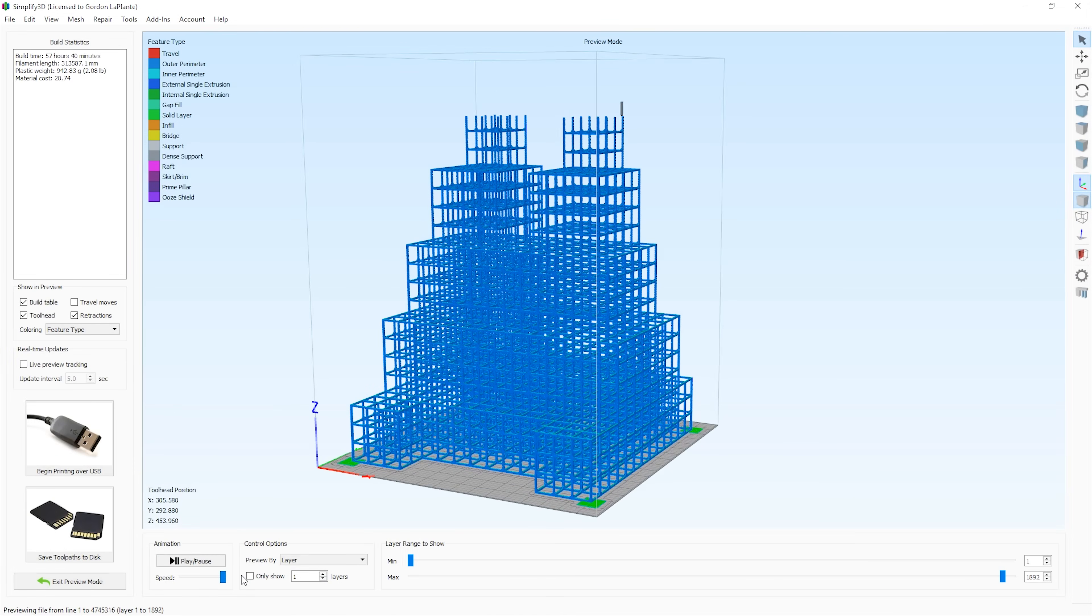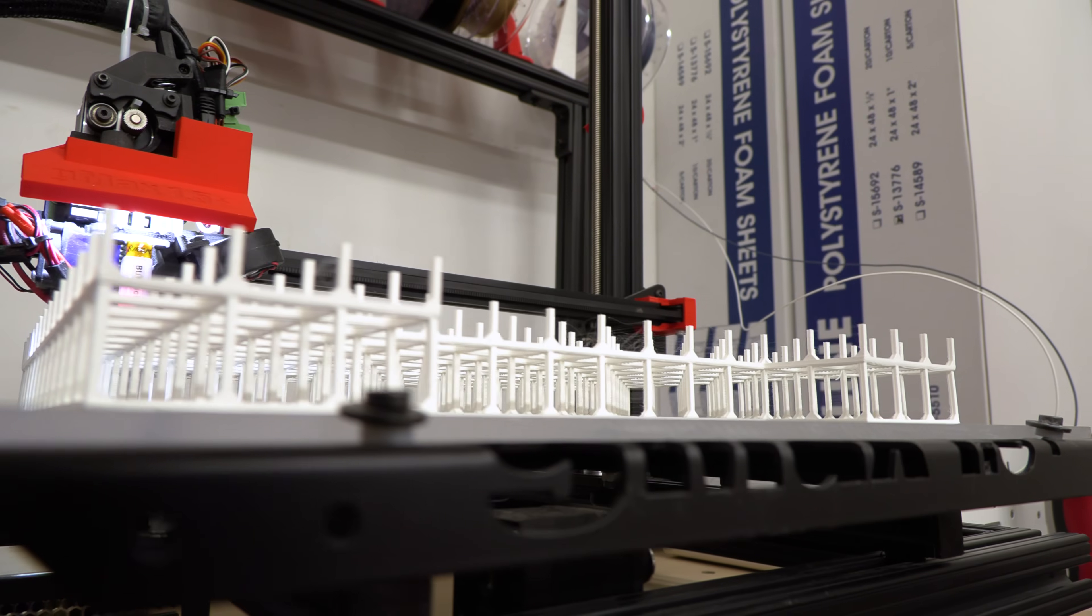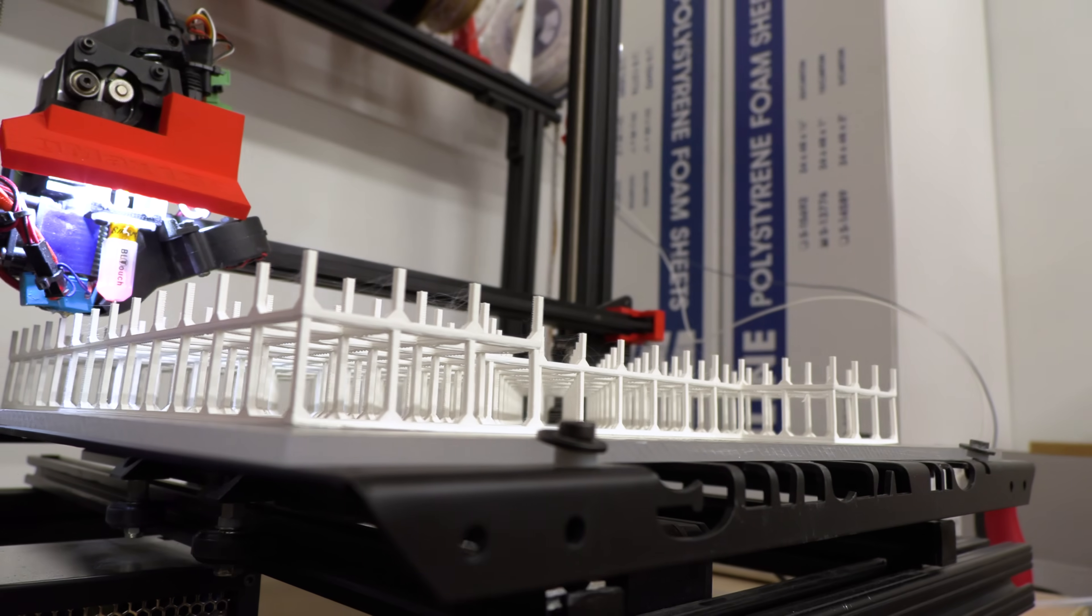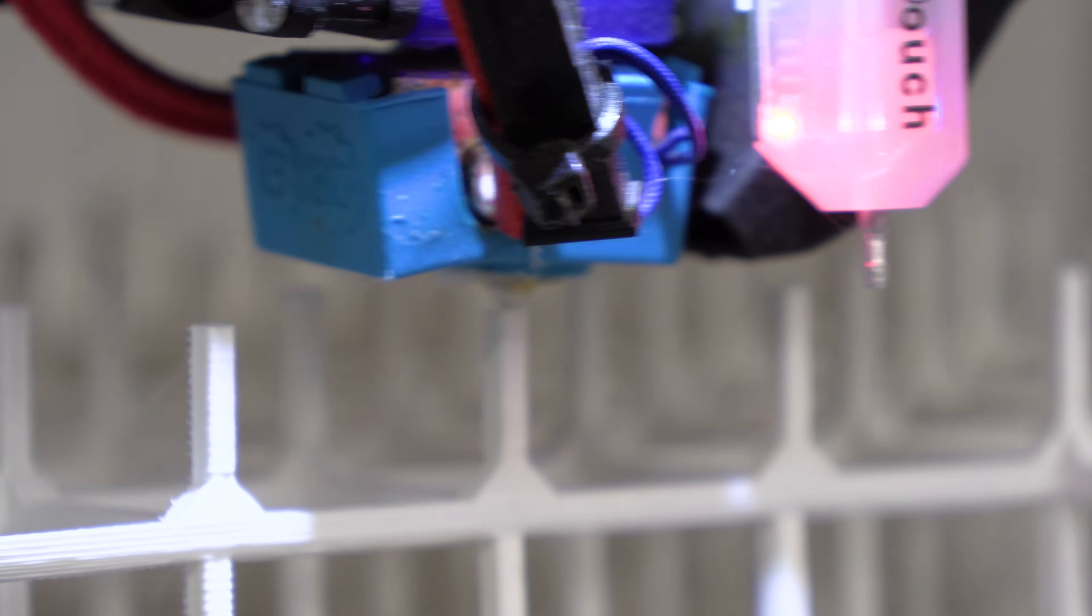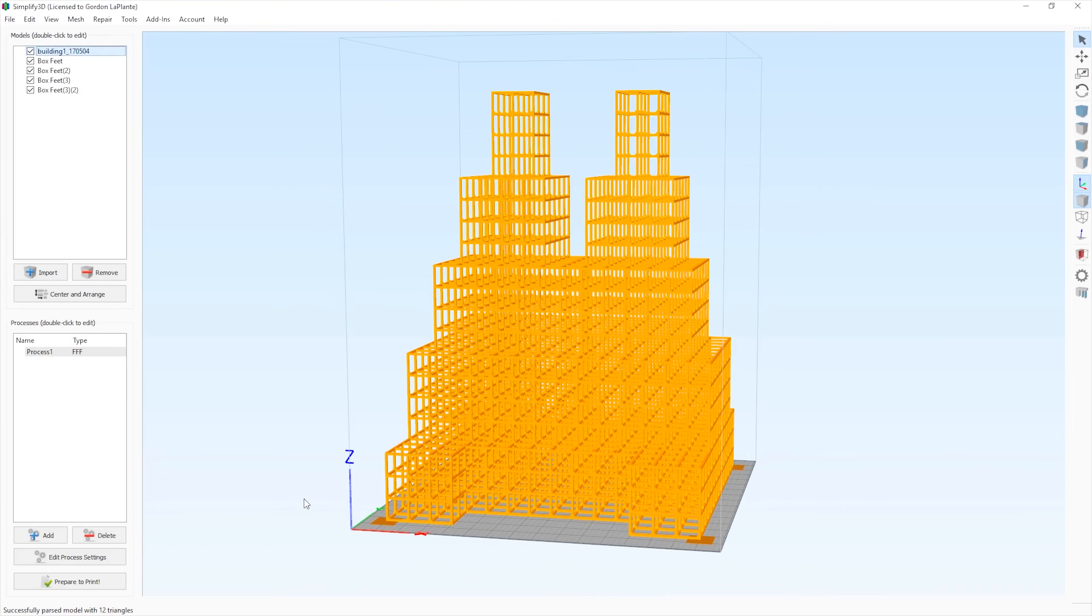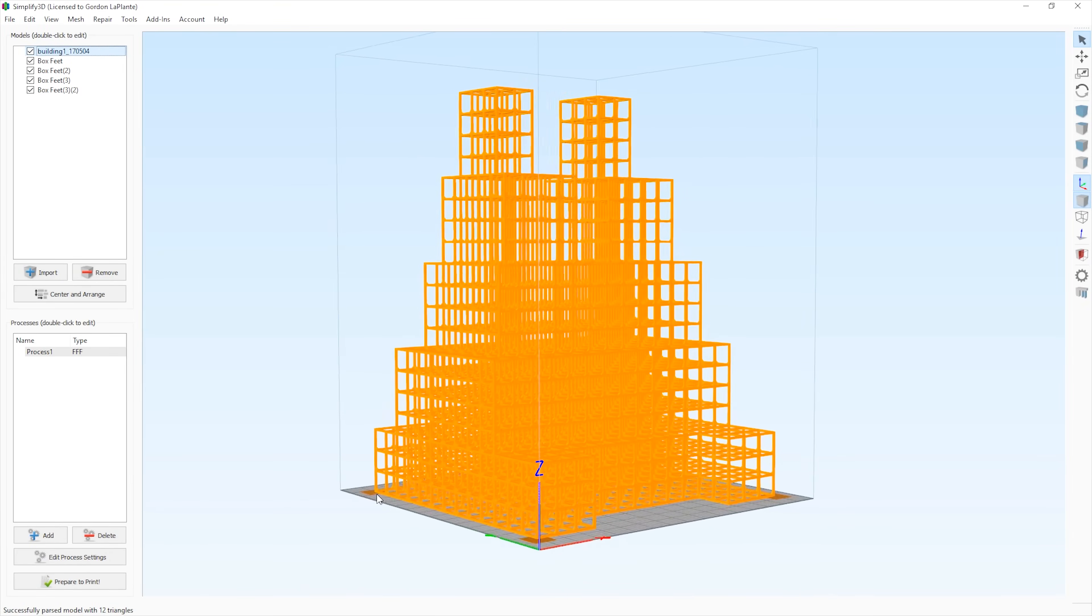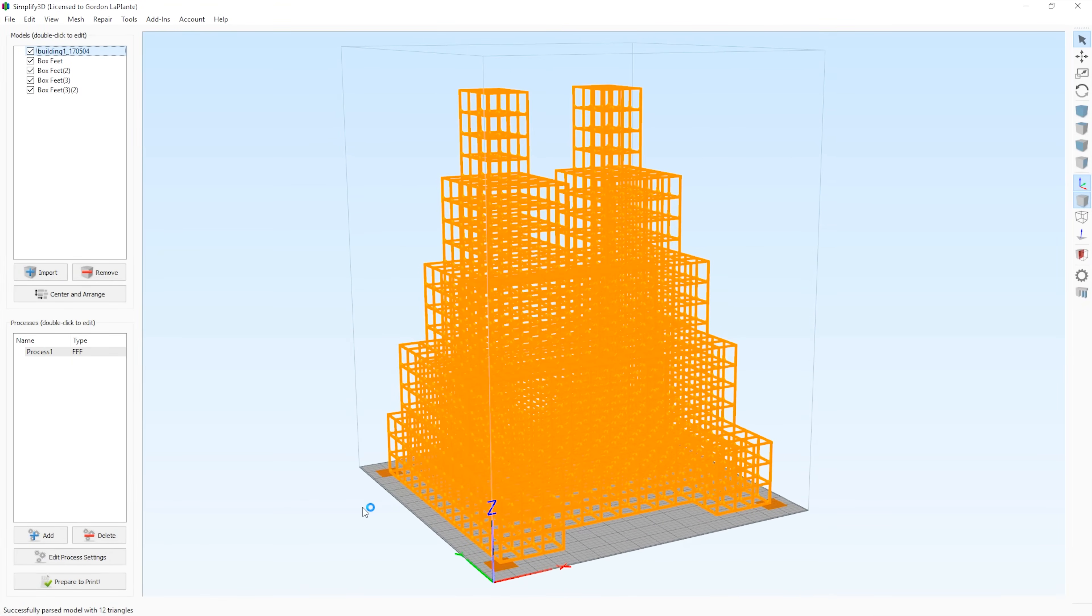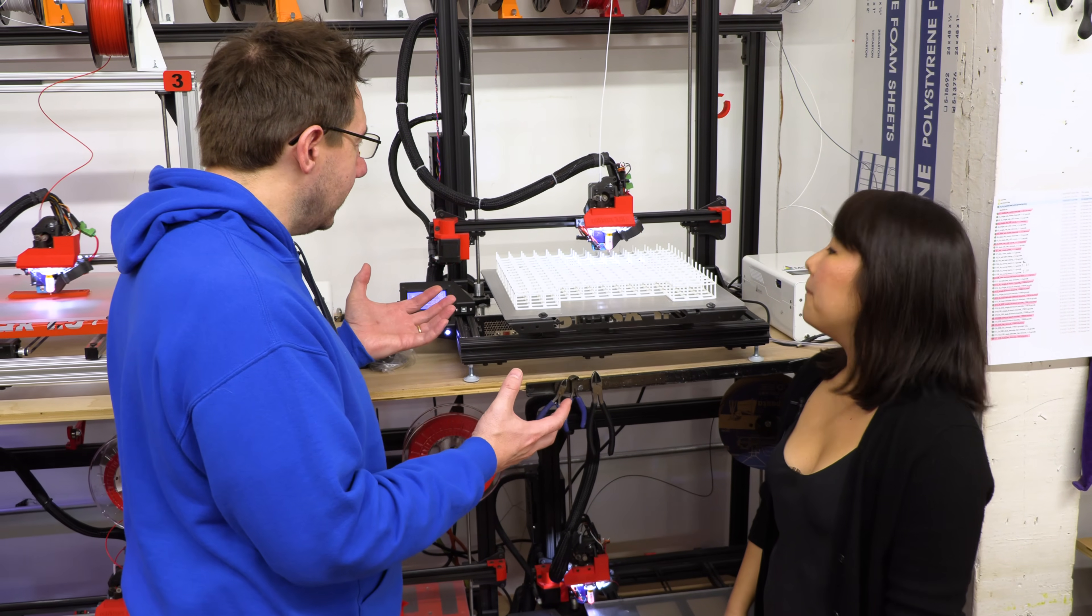Is there something special that you have to do to be able to print this? I mean, you really just want to dial in the retraction settings. I think that we dialed this in at about one millimeter and we're using really good filament. We're really happy with the Matterhackers Pro series. So we're printing that at about 200°C at the moment. And cooling. How much filament is this going to use when it's all done? Ultimately, actually less than a spool. I guess it's mostly open space. Yep.